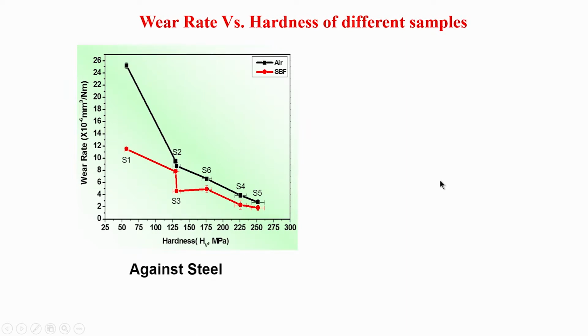In one of the earlier slides I mentioned that hardness differences should be considered while considering the differences in wear rate. In this slide, wear rate is plotted against hardness of the flat materials. We are not considering here the hardness of the mating materials, but this is against steel.